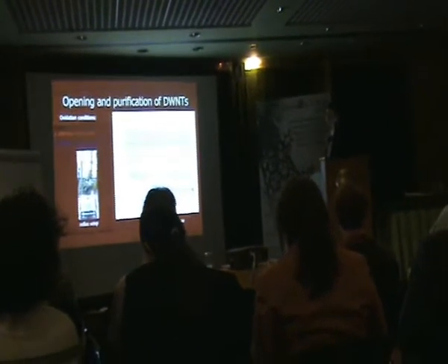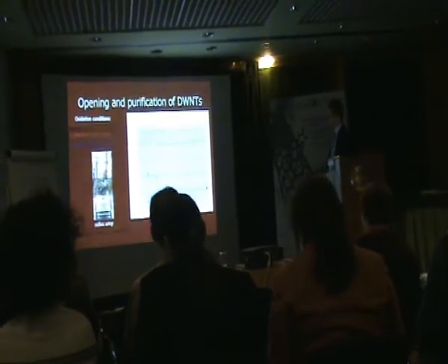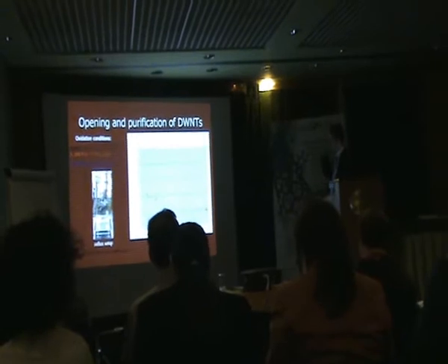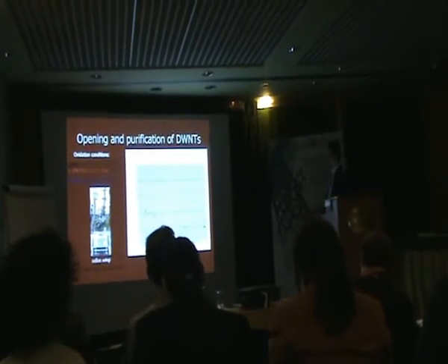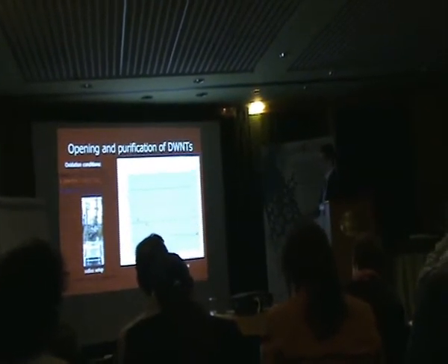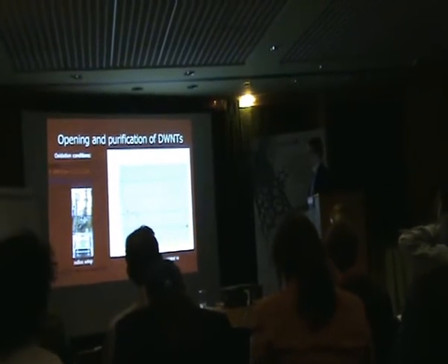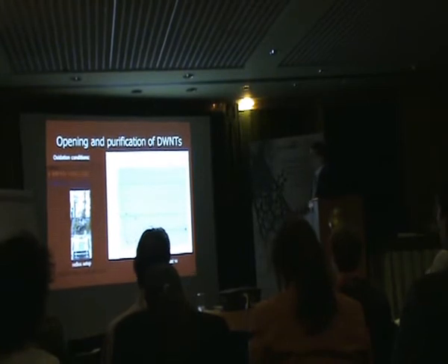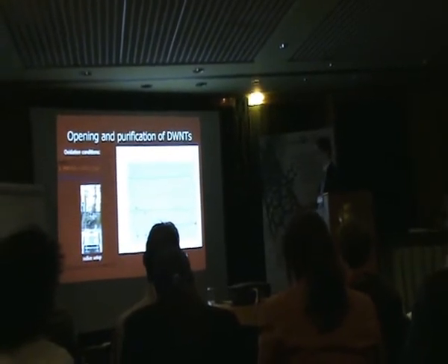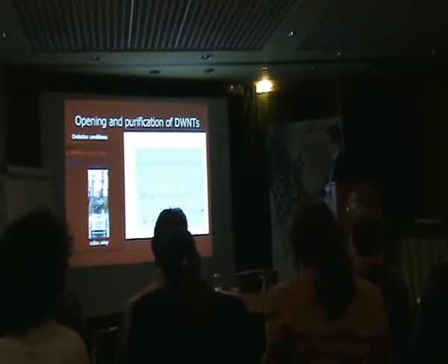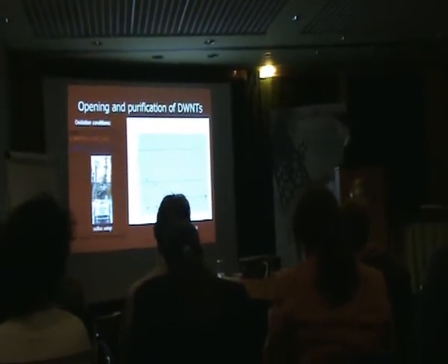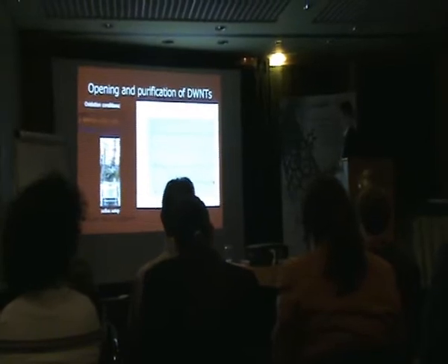From the results which we receive for carbon percent after oxidation with these two agents, we can conclude that after 3 hours of oxidation, we have better results with a mixture of sulfuric acid and potassium permanganate. The situation after 24 hours is almost the same for these agents. We have the same oxidation.